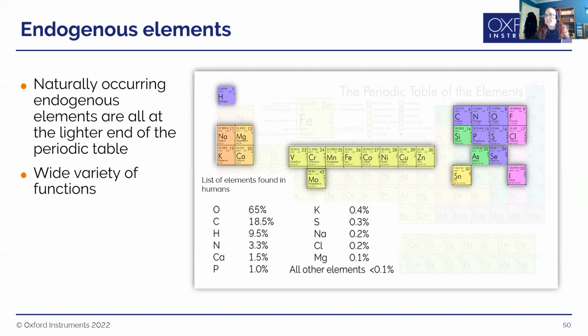Now, there still isn't a definitive list of essential elements for any species, which I find quite shocking and surprising. But this is for humans, and these are the relative percentages in humans. And you can see that these elements here become trace elements. So it's much harder to actually pick them up using a technique such as EDS. It is possible in some areas, and it is possible where you see an enhancement or an accumulation of these signals. Once you get to below 0.1 weight percentage, it becomes quite challenging. But all the other elements are readily detected, and different tissues and different cells have different levels. This is an estimate over an entire human being.